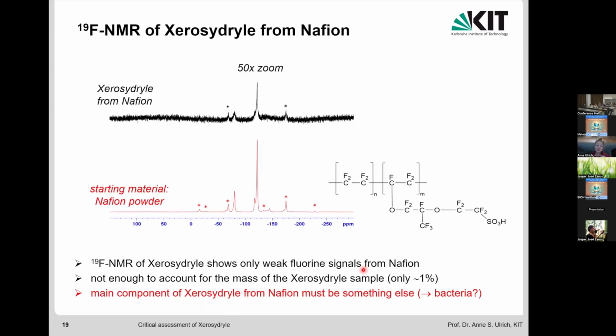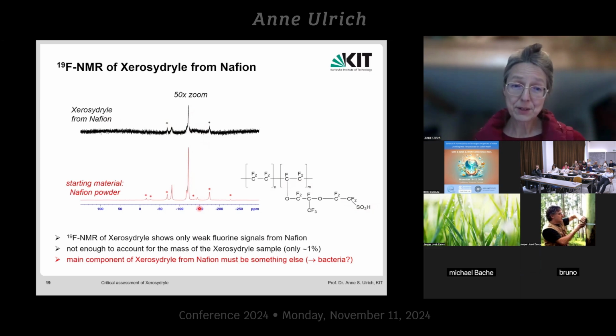Now, we continued with yet another sample from Nafion, and that was the Xerosydryle prepared from Nafion. This is the fluoropolymer with the acidic groups shown here. And since fluorine is a very sensitive NMR nucleus, we thought, wow, let's look at the fluorine NMR spectrum of the solid Xerosydryle. And interestingly, at this point, we hardly saw anything. A very weak fluorine NMR signal compared to a huge signal in the starting material. Now, this told us the Xerosydryle sample that was prepared from Nafion was not full of organic material, and it was not full of starting material. It was full of something else, but that something else was not H2O. So what could that be?